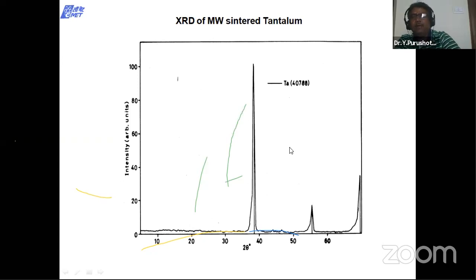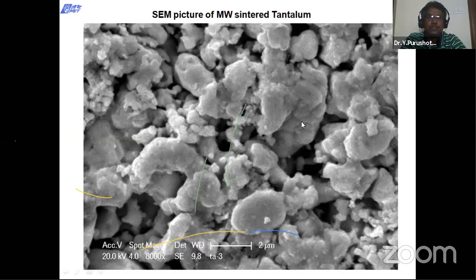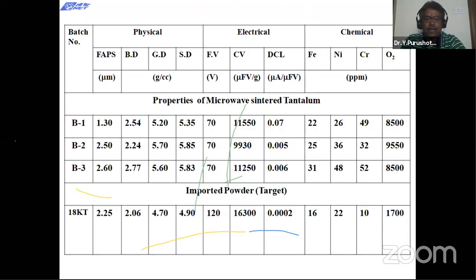This is another refractory metal powder, tantalum, which is phase pure tantalum, and this is the microstructure. This tantalum metal powder we prepared is for capacitor applications. For capacitor applications, if you sinter, a porous structure is required. So whether we will get a porous structure or not by microwaves, we made one attempt. We got a porous structure, and we compared the conventional sintered and the microwave sintered.